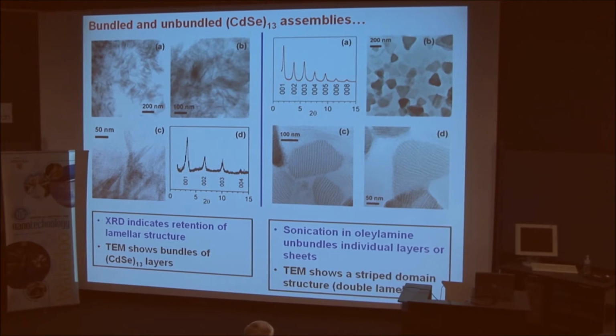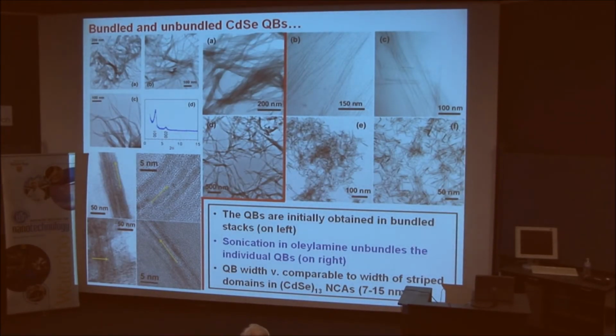Okay, now after we heat these structures, we get these wispy bundles, which turn out to be stacks, vertical stacks of quantum belts. And they can be unbundled, as I showed you there, to give individual quantum belts. So let me put all of this together. Finally, as I said before, the width of these quantum belts is about 7 to 15 nanometers, which was the same dimension as the striped domains on the previous slide.